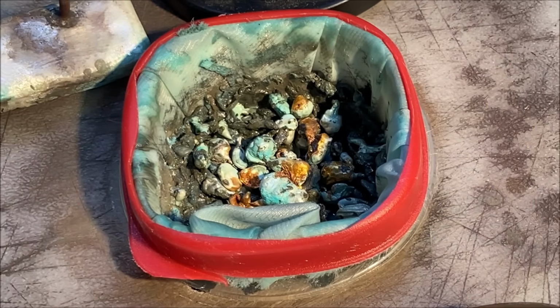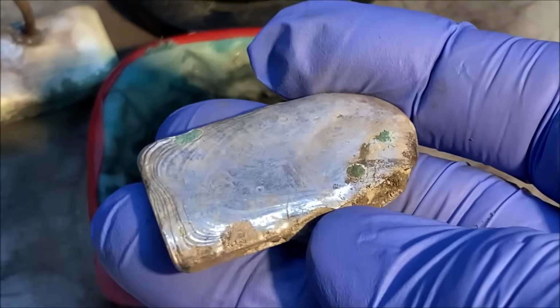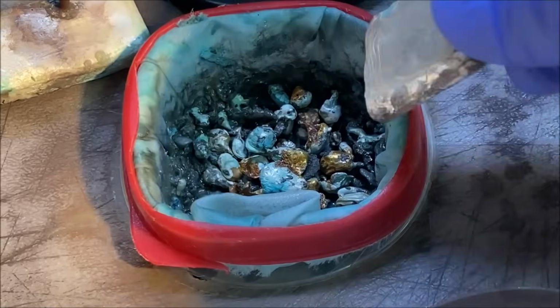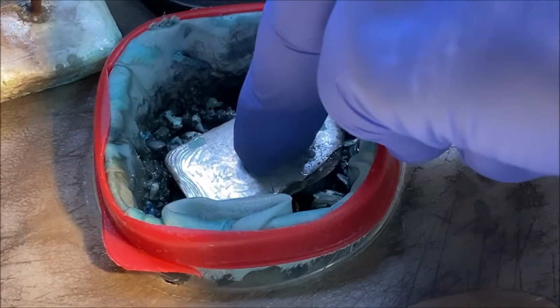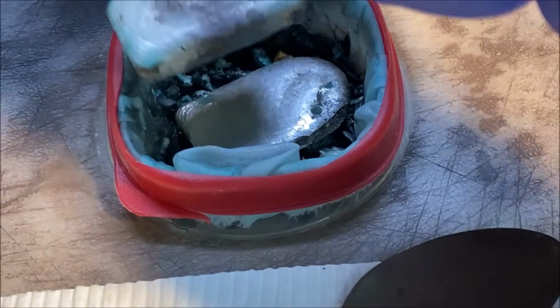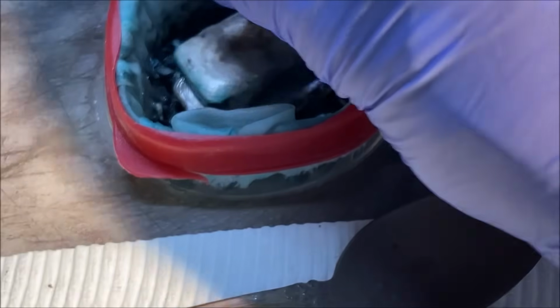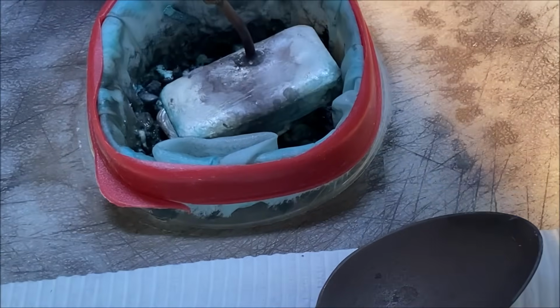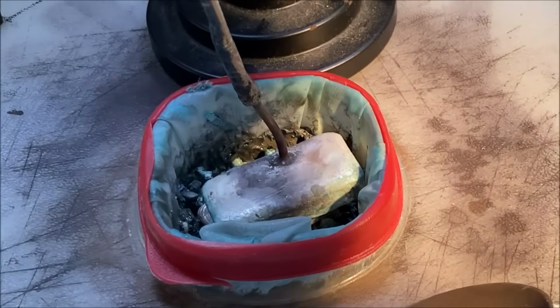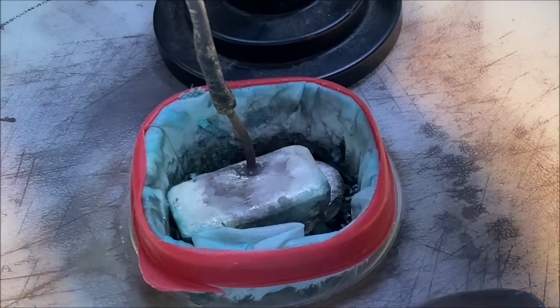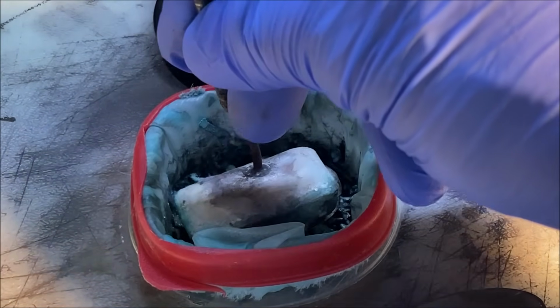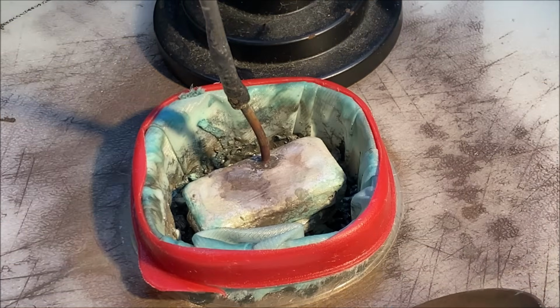So in order to prevent that, what I've got is a silver bar. And I'm just gonna set that in here. And I'm going to put the electrode bar on top of that, and that should prevent us from making contact with the electrolyte and having our anode electrode bar dissolve. And we don't want our anode electrode bar to dissolve because we can use it over and over if we keep it up out of that electrolyte.